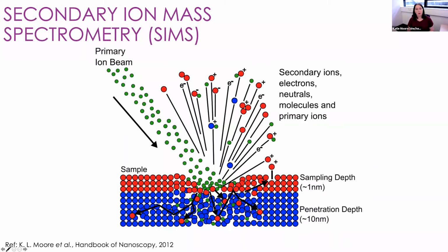NanoSIMS is based on the principle of secondary ion mass spectrometry, known as SIMS. With this technique, we use a charged, focused primary ion beam to bombard our sample surface. This results in removal of the top few atomic layers of our sample surface in a process known as sputtering. In that process, we generate a range of different species that come off our sample surface, from secondary ions to neutrals, molecules, and resputtered primary ions. It's actually only the secondary ions which we can analyze and collect.